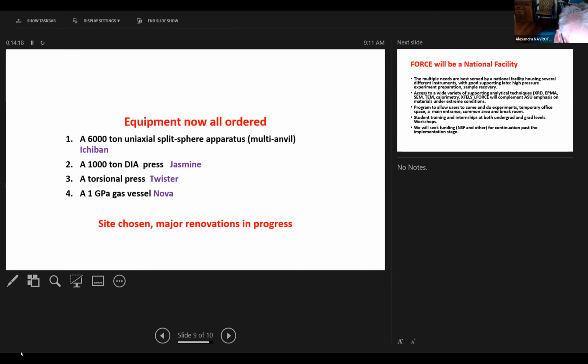The pièce de résistance is a 5,000 or 6,000 ton uniaxial split sphere apparatus, a so-called multi-anvil, which we've christened Ichiban, and which we are getting from Sumitomo in Japan, and which Japanese research groups have a lot of experience with. Its comfort range for operation is up to about 25 GPa, and its temperature ranges up to about 2000 degrees C, depending on what sort of sample assemblies and heaters. These are typically resistance heaters that you put into the apparatus. And the samples that can be made range from being several hundred milligrams in the lower pressure range to a few milligrams in the highest pressure range.